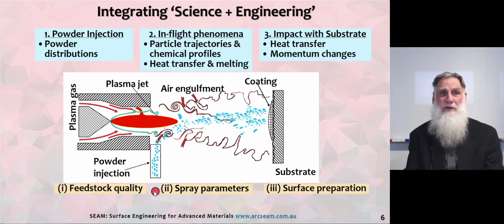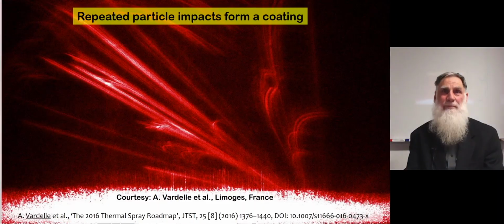So there are many aspects within this process which require control. Otherwise, the quality will be quite severe. So the 3 major ones which I've picked out here would be feedstock quality, the spray parameters, and the surface prep. So in this introductory part of my talk, I'm going to describe how the process zone impacts and affects the coating quality. And if we can change this process zone, then we can actually change the coating quality and the attributes so that the performance can be enhanced.